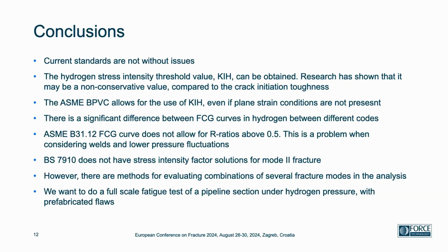Yeah, there's a difference between the fatigue crack curves, and I would think the ASME code needs to implement something that goes for an R ratio above 0.5. And yeah, the BS 7910 does not have stress intensity factor solutions for the mode 2 fracture. However, there are methods for evaluating combinations of several fracture modes in the analysis.